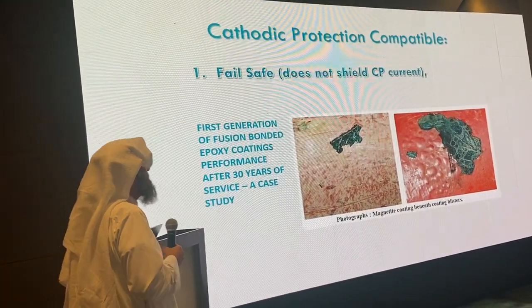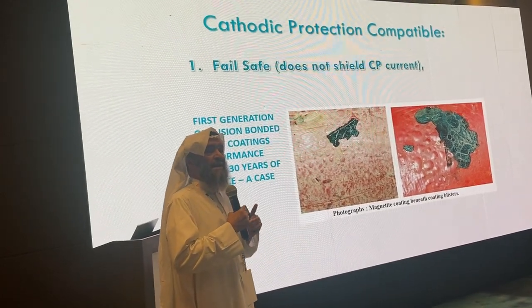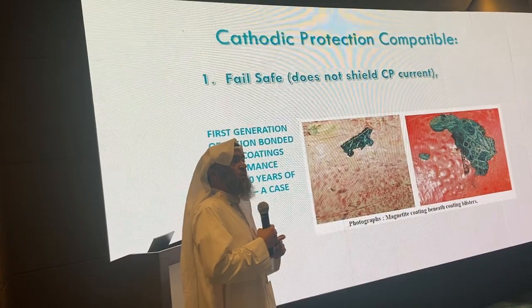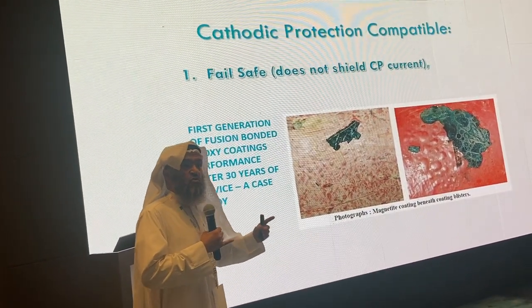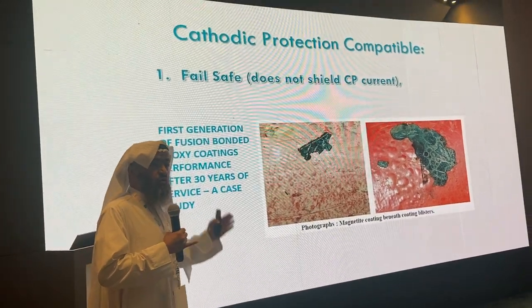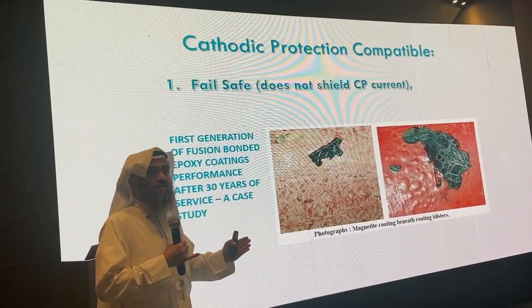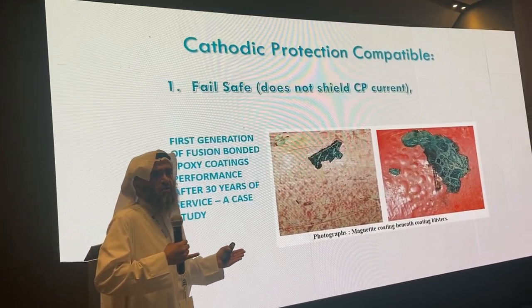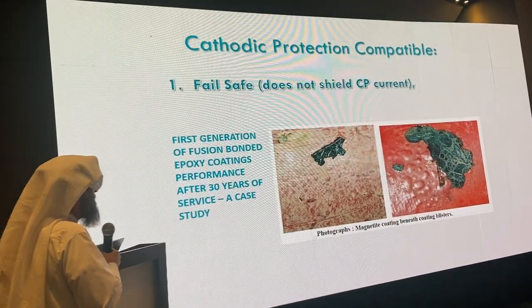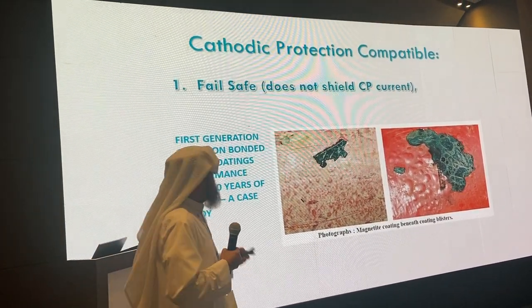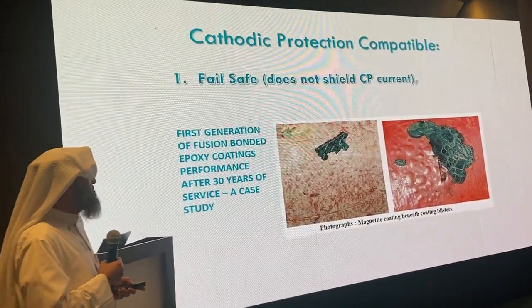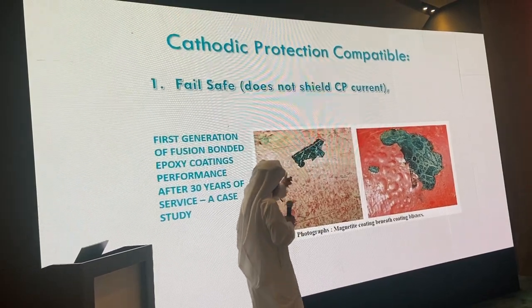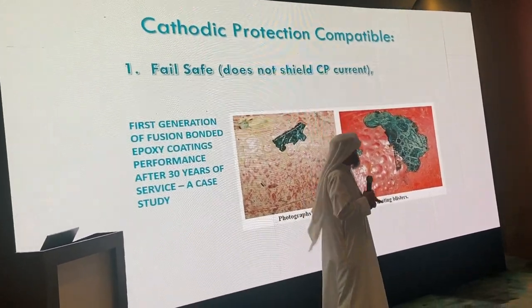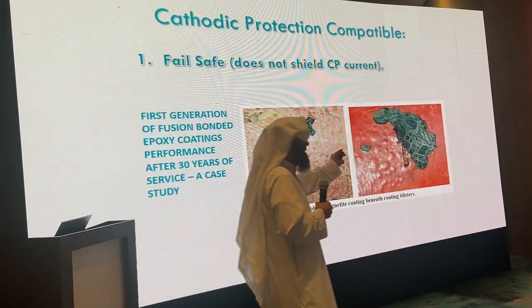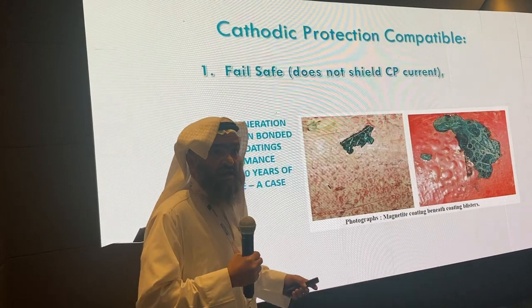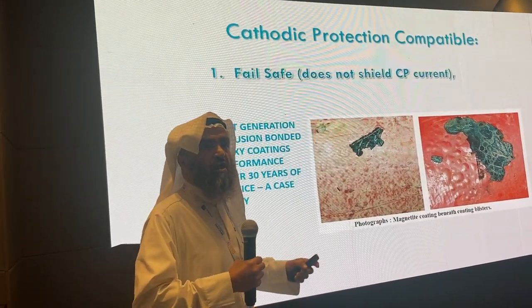Now, what do we mean by cathodic protection compatible? We mean that if the coating fails, it will allow the current of the CP to go through. If it protects or prevents or shields the cathodic protection, there is no use then to use the cathodic protection. An example of fail-safe material is FBE. This is a first generation of fusion bonded epoxy, where, as you can see, it is a very poor type, a lot of blisters. Nevertheless, there is no corrosion. It's all black, magnetite, no trace of corrosion. Why is that? Because FBE doesn't shield your cathodic protection.